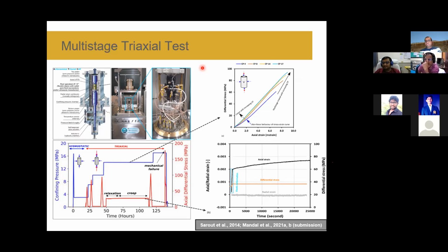We have also tried with some other samples, not shale, like pure sandstone or limestone, where saturation can be done quickly. So we have already checked what impact it has if you do saturation or do not do saturation. It's not that much in this case, because you are mostly looking at nano-Darcy permeability rock, where the poroelastic effect is probably negligible.